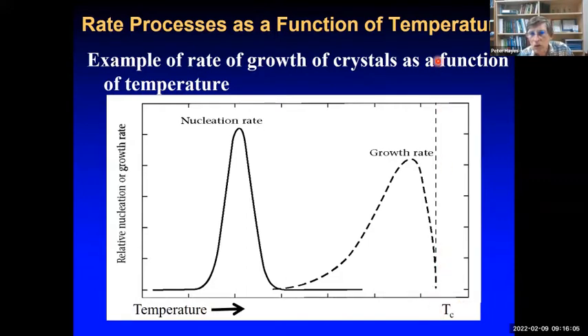And this TC, this vertical dotted line, is telling us the critical temperature. So at temperatures above TC, this new product will not appear. There's no thermodynamic driving force for formation. Below that, we see that as we lower the system below that critical temperature, the reaction rate or the growth rate actually increases with lowering temperature. So thermodynamic driving force increases. But we get to a maximum here, and if we go to lower temperatures, we find the rate is actually dropping off.